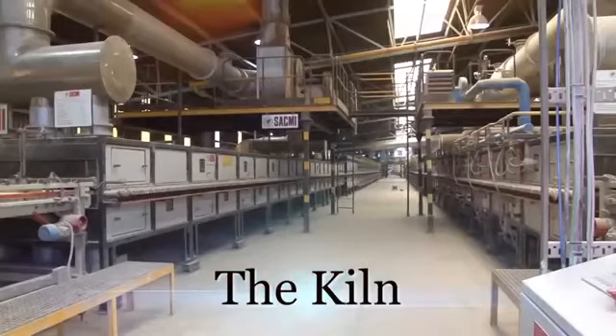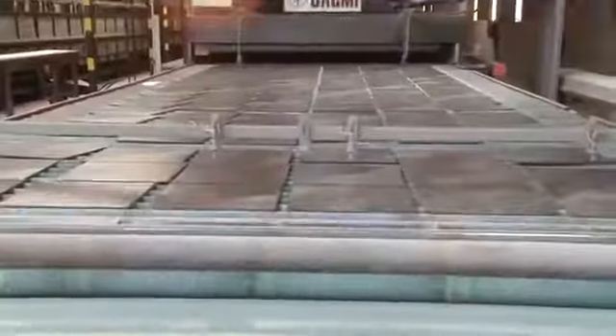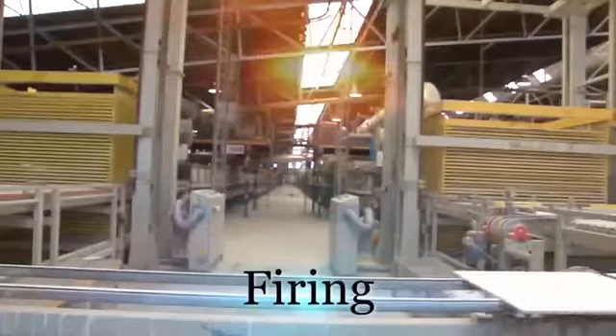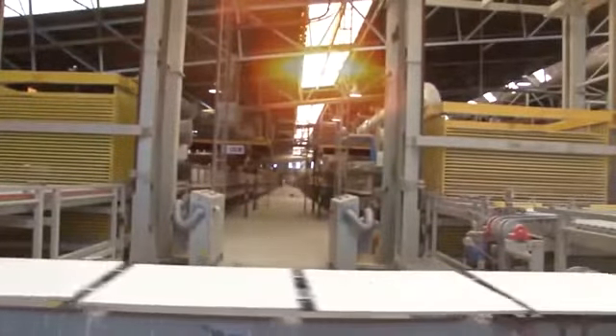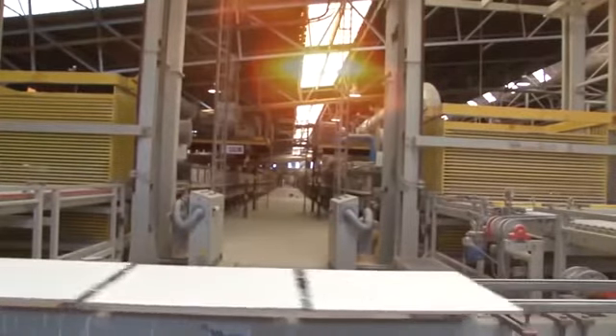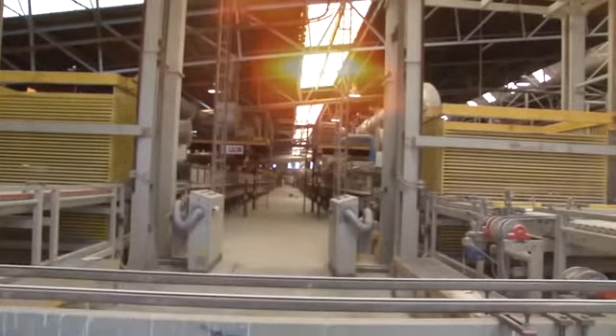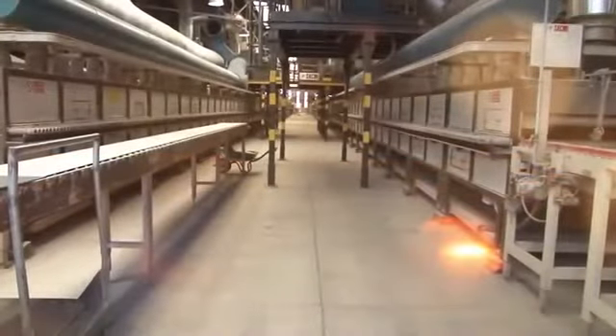The kiln is a long tunnel heated by gas heaters, through which each tile passes in a process known as firing. In the first section of the kiln, the tile is dried at low temperature to remove water from the clay. If the tiles were subjected to very high temperatures in this first phase, the water in the tiles would turn to steam, and many of the tiles would explode. Once the tile has been dried sufficiently, the temperature in the kiln is raised to 1185 degrees centigrade. This is where the tile is fired to bake the clays and other materials that are in the body of the tile.